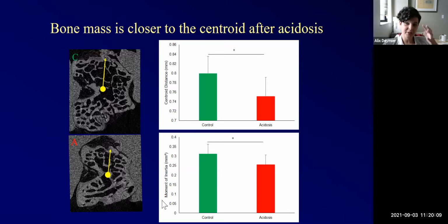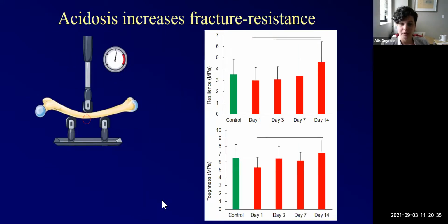So 14 days, I'm getting all these chemical changes, but these cells must also be reworking the organization of my bone. So I'm thinking, man, like maybe the cells are a pretty big deal here, right? If I have a change in composition and I have a change in shape, then it's pretty likely that I'm going to have a change in mechanics. So we take these same bones and we ended up doing 3-point bend. Now, what we find in the 3-point bend results is that we don't have a lot of changes in things like stiffness and strength, but we do see an increase in resilience and an increase in fracture toughness. Now, this may seem surprising because I told you earlier we're going to get increased fracture clinically, but the early stages of acidosis effects on bone actually does show an increase in toughness followed by an increase in fracture.